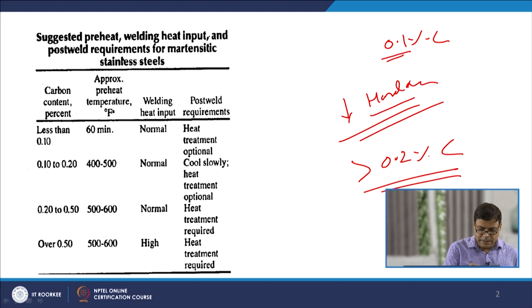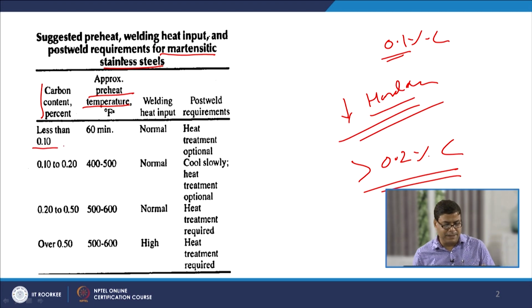So, this table is showing the preheat temperatures to be used in Fahrenheit as a function of the carbon content present in the martensitic stainless steel. For low carbon content, normally the preheat is not used and we may get a successful weld joint without any tendency for cracking. The minimum preheat is 60 degree Fahrenheit. In any case, if the ambient temperature is very low, then the minimum preheat of 60 degree Fahrenheit is to be used.